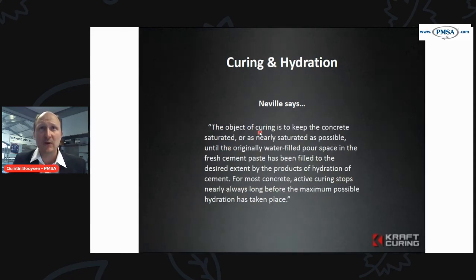The object of curing is to keep the concrete saturated or nearly saturated as possible until the original water-filled pore spaces in the fresh cement paste have been filled to the desired extent by the products of hydration of cement. So it's really giving that cement a chance to fill all those little voids, those micro voids, right up front as the gel formation and the fingers start to grow.